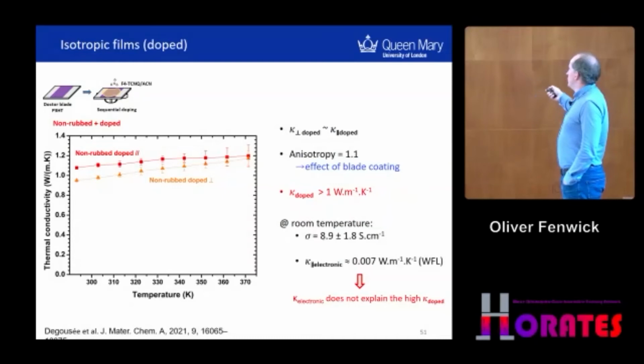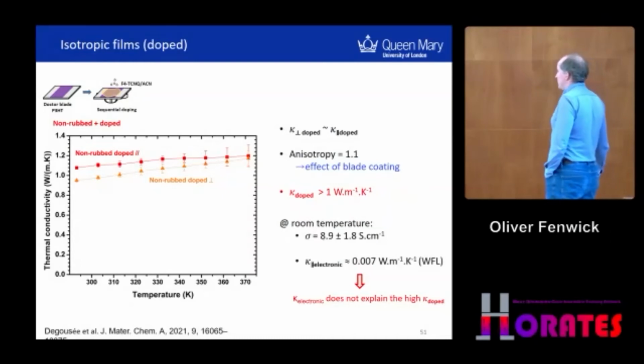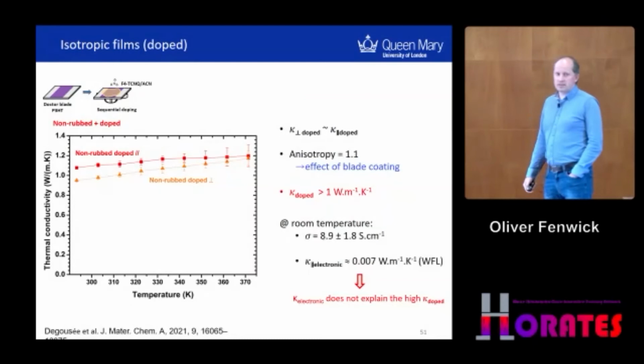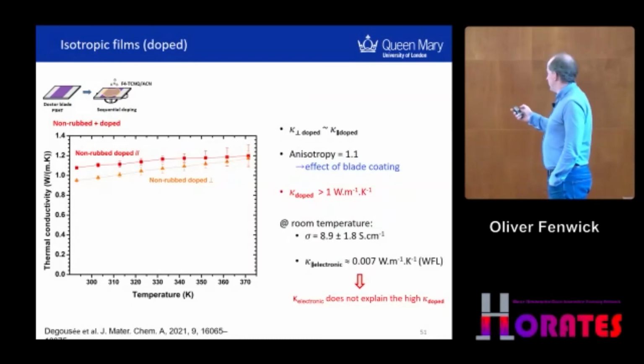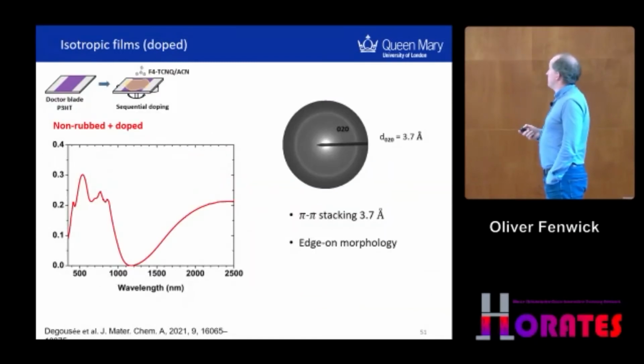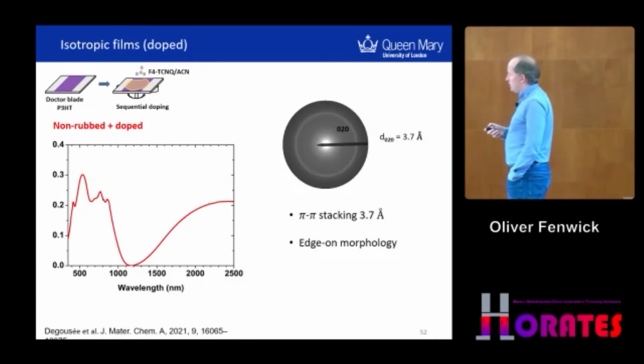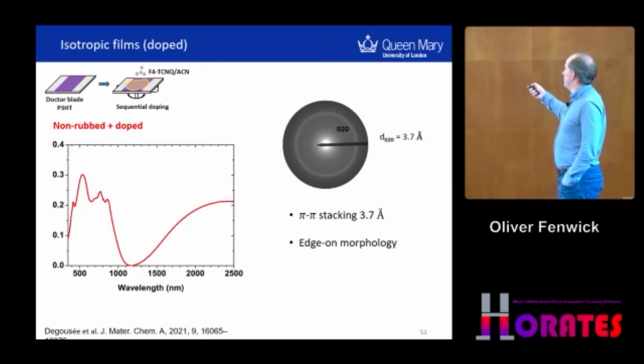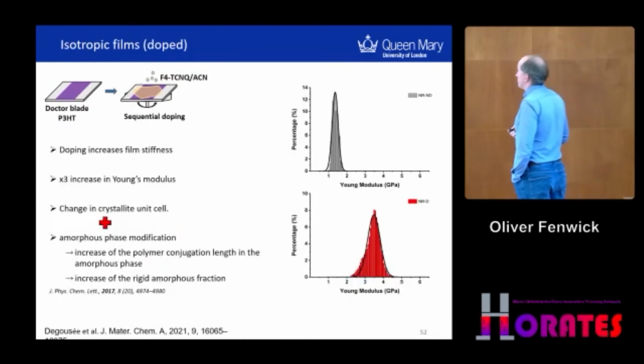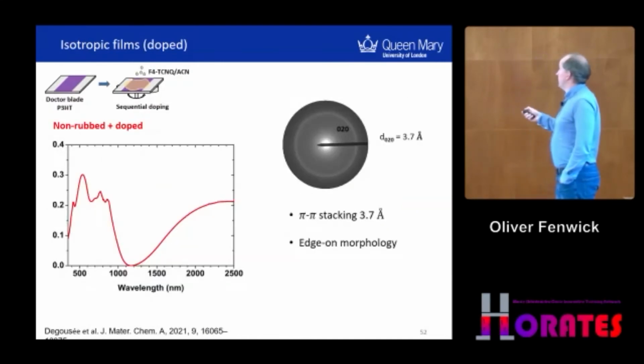If you look at this, could this be an effect of an electronic component of the thermal conductivity? No, it can't. It's way too big for that. The electrical conductivity is lower in this case than the aligned polymers. So something else is driving that. The pi stacking is reduced again from the undoped case, so in that direction there might be improved thermal transport. And we still have an edge-on morphology. And that might be quite important.